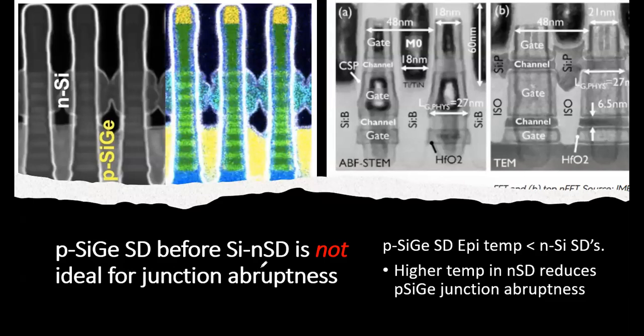So no wonder p-SiGe source and drain before n-Si, I would say, is not ideal for junctions. The problem is that in this case, Si&Ge channel, Si&Ge source and drain on the bottom has not only the defect issue, but also temperature issues. You look at the picture on the right here, the boron here.